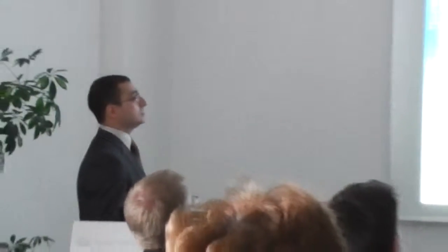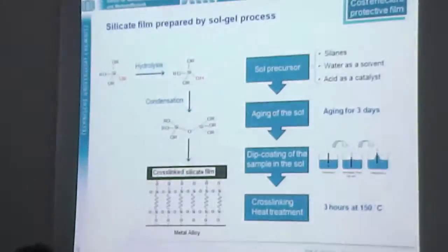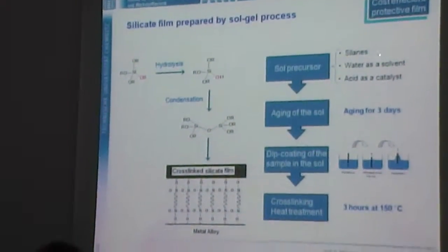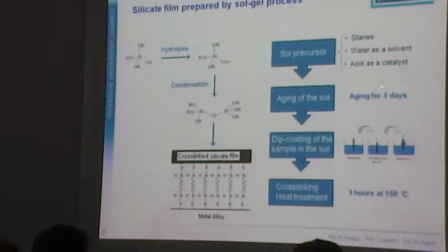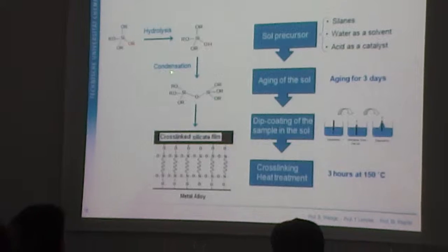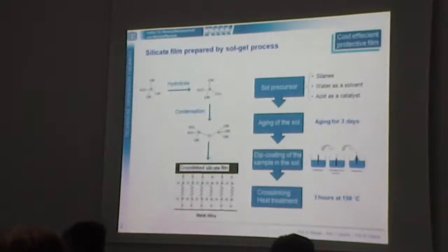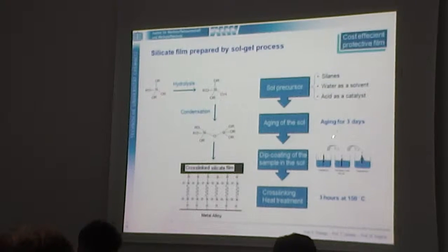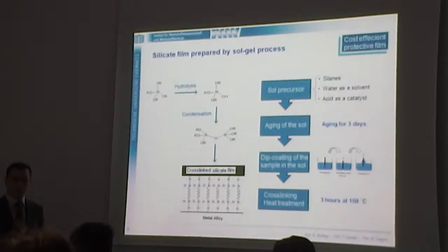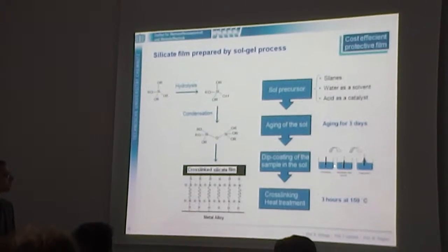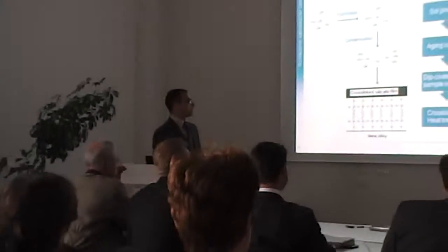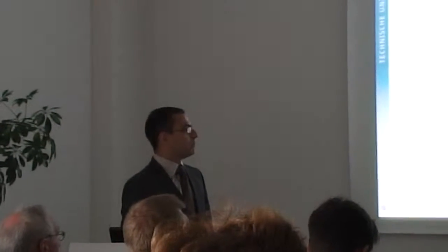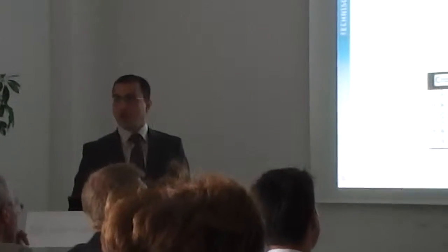The silicate films in this work were prepared by the following steps: silanes with deionized water and hydrochloric acid as a catalyst. The mixture is aged 3 days at room temperature. During the aging period, hydrolysis and condensation reactions take place. Monomer turned to dimer and then particles. After 3 days, the film was applied on the aluminum and magnesium substrate by dip coating. The cross-linking of the silicate film was carried out by heat treatment, 3 hours at temperature 150. After this heat treatment, a cross-linked film can be formed on aluminum or magnesium substrate.